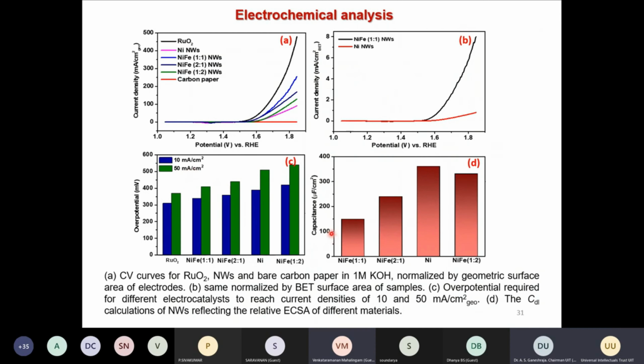And to understand why there is an increase in activity for nickel iron compared to only nickel wires, we have done the capacitance as well, the electrochemically active surface area through Cdl measurements. What we see here is interesting. The overpotential is better for the nickel iron 1:1 nanowires, whereas here a high surface area is found for nickel, though the nickel activity is very low, with high overpotential. So this indicates that it is not the surface area, the number of catalytic active sites on the surface, but the intrinsic activity. Iron increases the intrinsic activity of nickel for the oxygen evolution reaction, which is well known. Of course, the mechanism has a lot of debate, but still iron improves the activity of nickel. This is very clear from this data.